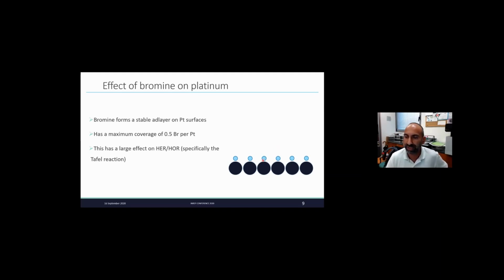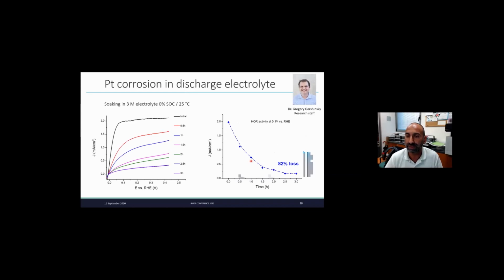So that would be the reaction that you have. And then you've got proton that is produced. But if you have some bromide on top of the platinum, even if you have this 0.5 coverage, then the hydrogen is sticking to the platinum, and then you don't have the second step, which is the dissociation, the Tafel step. So the reaction is blocked, and the catalyst is poisoned.